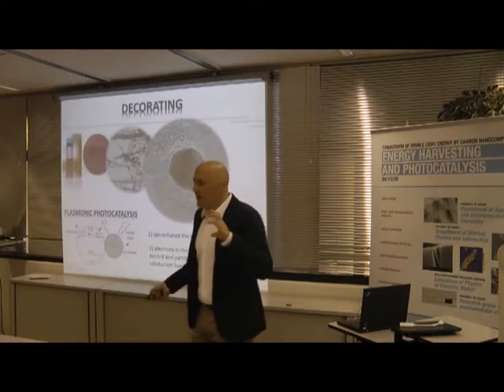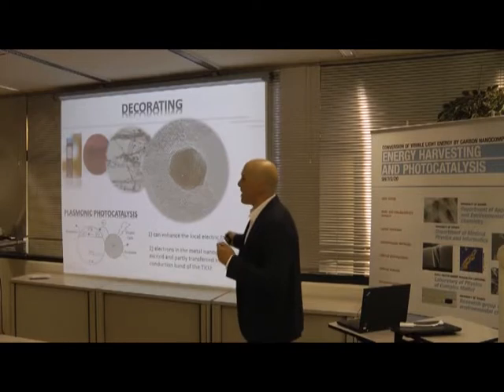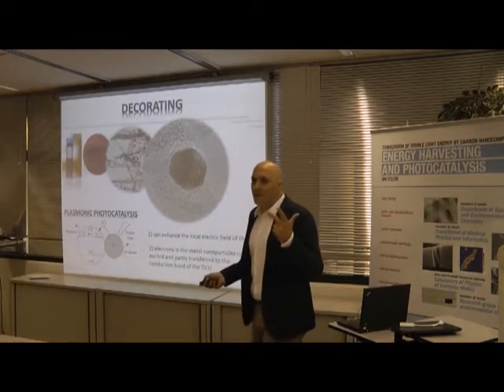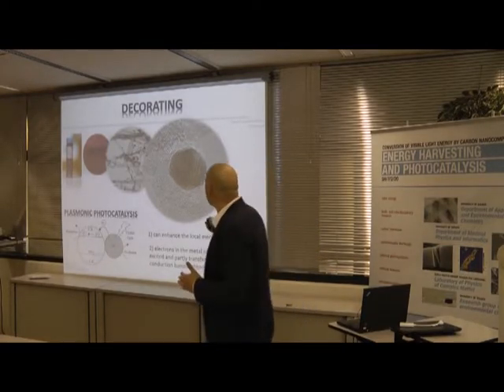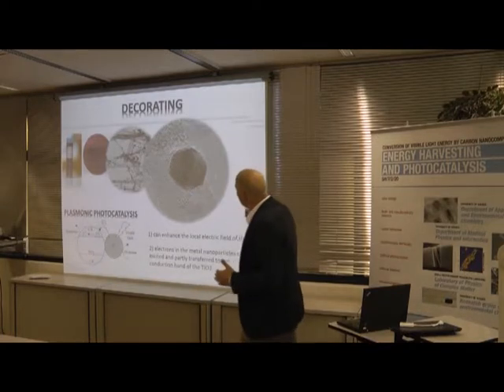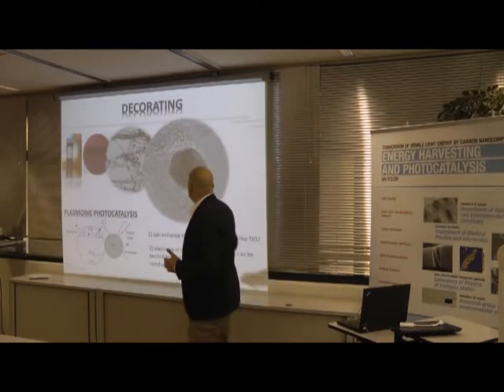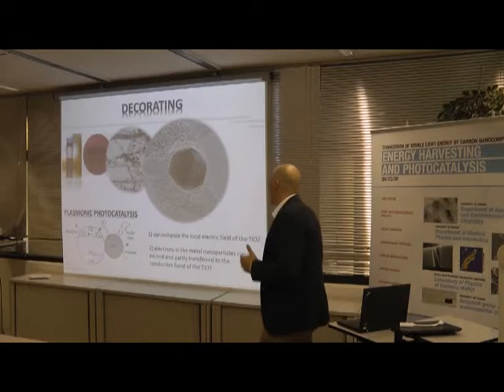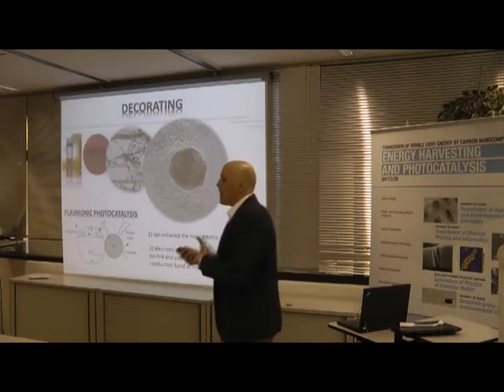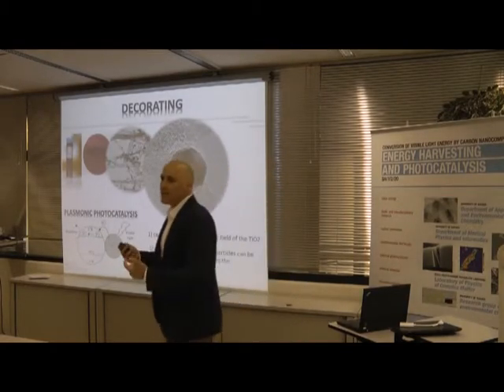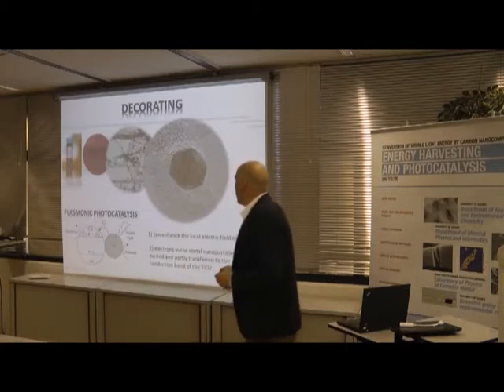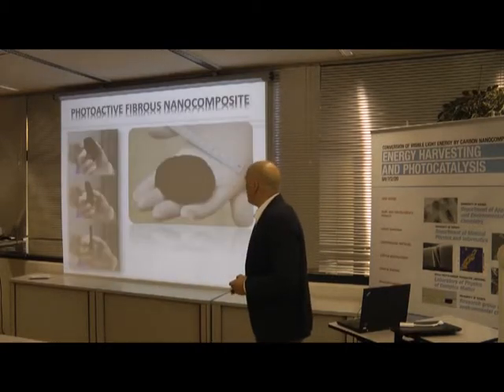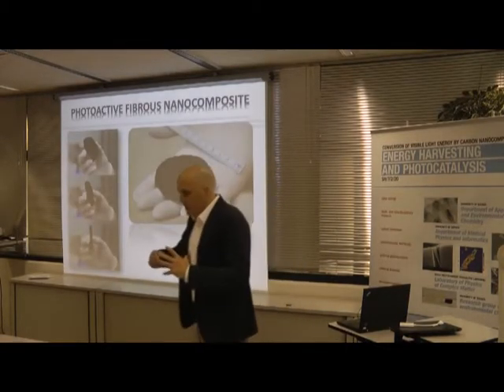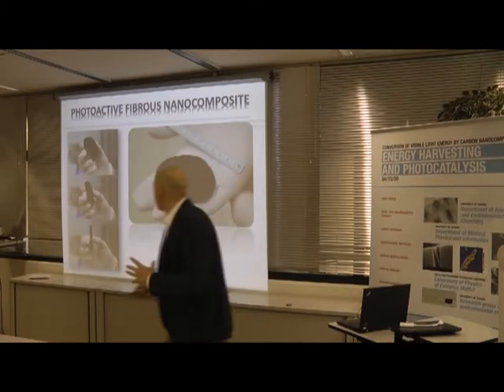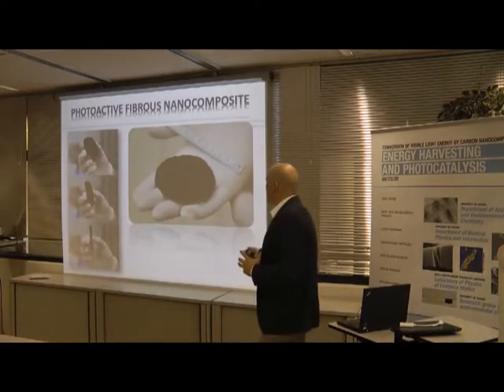And the other is the decorating. Usually people use platinum, rhodium, palladium, gold, silver nanoparticles to put on the surface, and where you put it, you can create this local electric field which could help you in the exciton dissociation and increase the photocatalytic activity. So finally, when we put together all these strategies, we ended up with a so-called optimized catalyst.